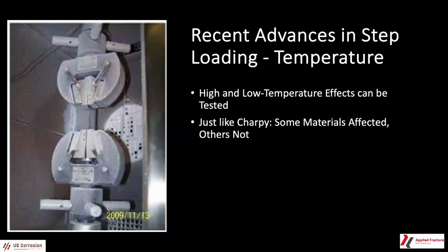Another area that we're working on a lot currently is temperature effects. A lot of the step loading and other hydrogen embrittlement research is done at room temperature. But what we find is for different materials, there are high and low temperature effects that are both interesting and really informative, because in some cases the embrittlement goes away and in other cases it becomes worse.